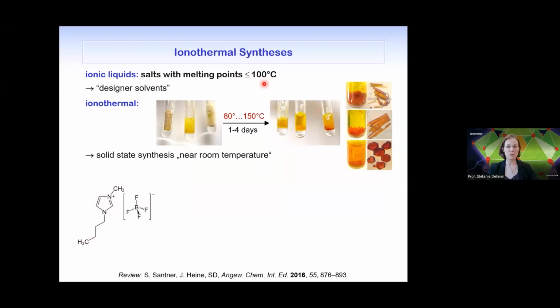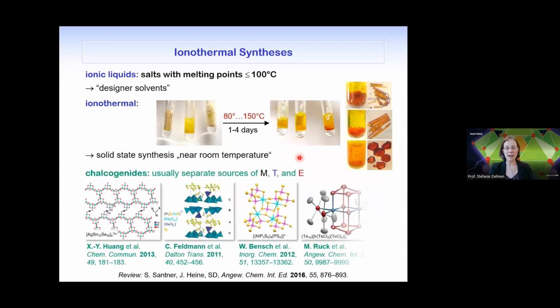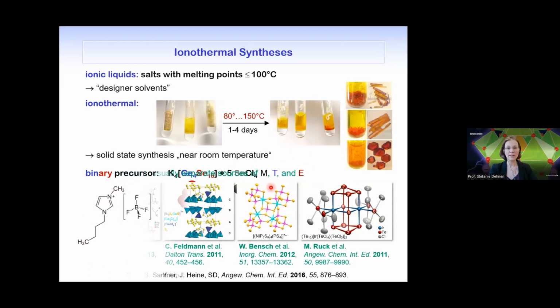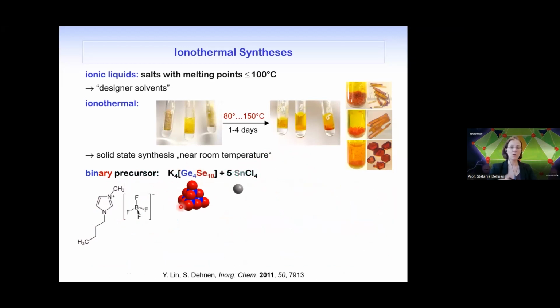You won't probably use your fingers to test the temperature, but it's still pretty low in regard of high temperature synthesis for solid states. Well, chalcogenides have been produced this way, but not too frequently before we started in this area. And all of the examples we found until we started used separate sources for these molecules, for these clusters and complexes. Our idea, as I said, is that we use binary precursors to control or to also skip some kind of an oxidation step in this chemistry, and then added some further component, like, for example, tin tetrachloride in this case.